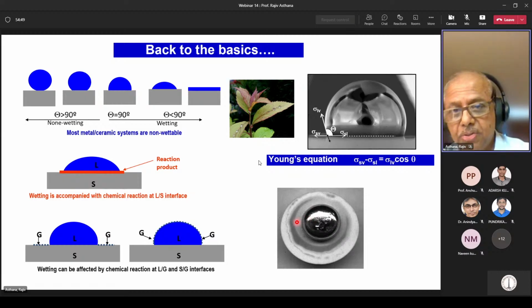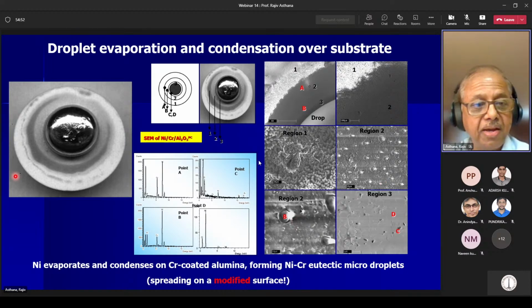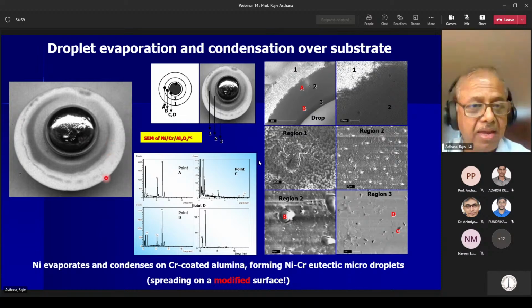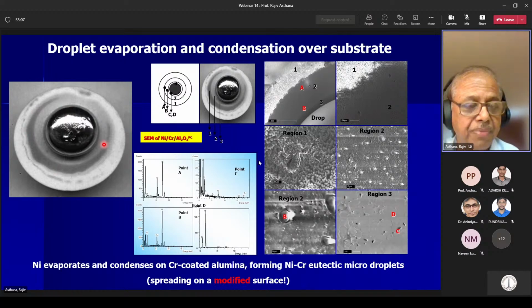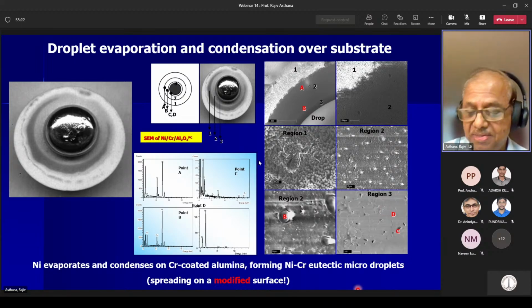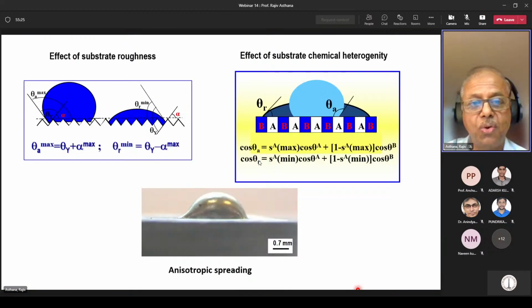Some of those things we looked at. Here is an example of a nickel droplet on a chromium coated aluminum oxide substrate. And what we see here is that during the testing process, there is evaporation and condensation of nickel vapor on the surface here, and it forms some little teeny eutectic droplets of nickel chrome over which this larger droplet is spreading. So these are very, very complex systems as compared to the low temperature systems.